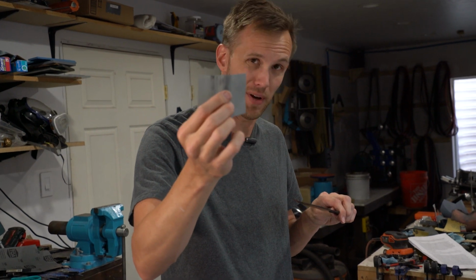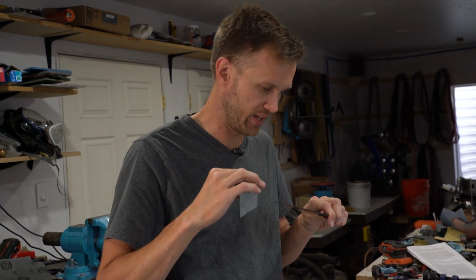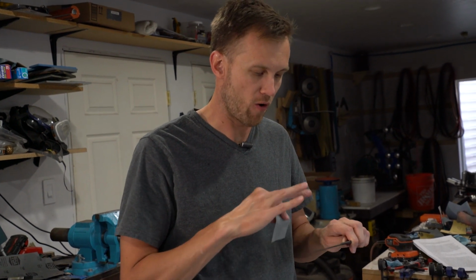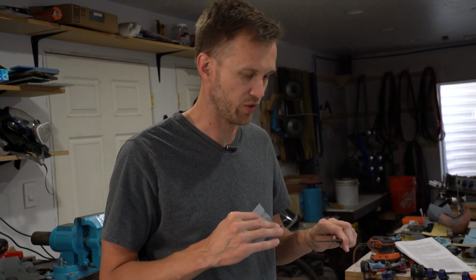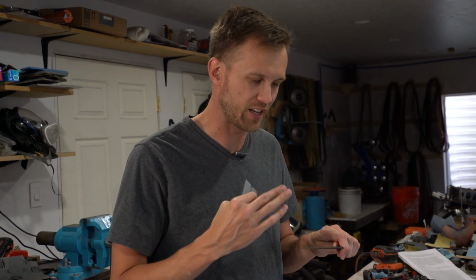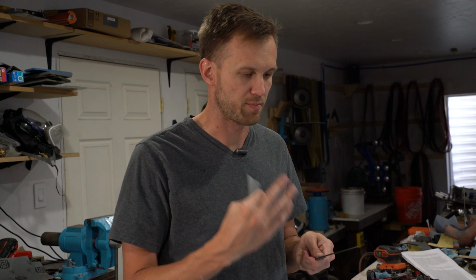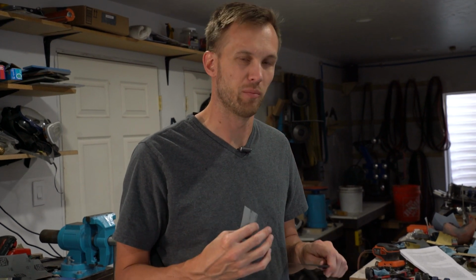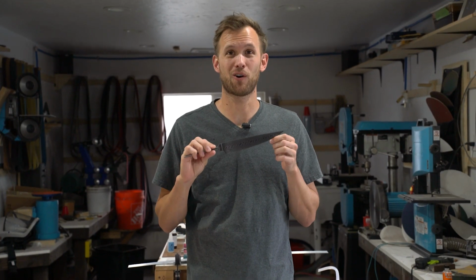But it doesn't take much to get one whole side of the blade going, and I think that's a much better silvery effect. Really gets the contrast that we're hoping for more than just using the cloth. Not that using the cloth is the wrong thing, just that because I got too much oxide buildup from its bath in the ferric chloride, I needed something a little bit more aggressive. At this point, I am going to call the blade done, and that's where we're going to end part 1 of the knife build video.